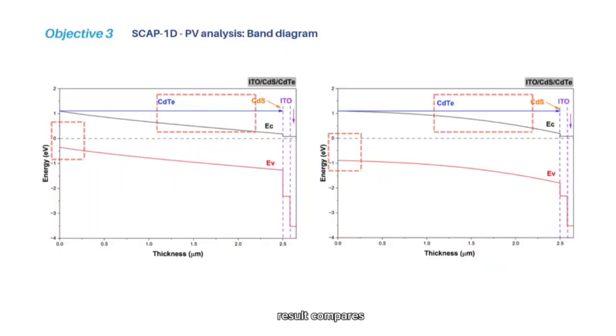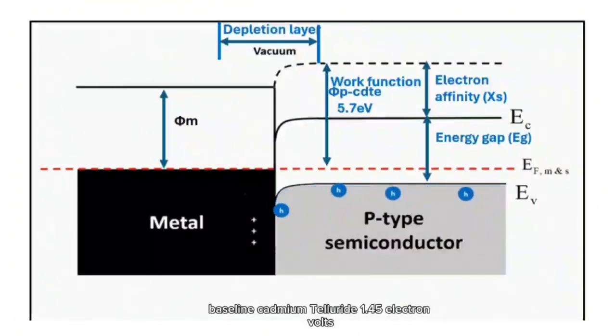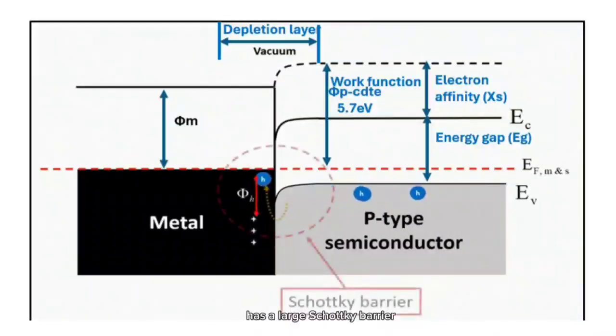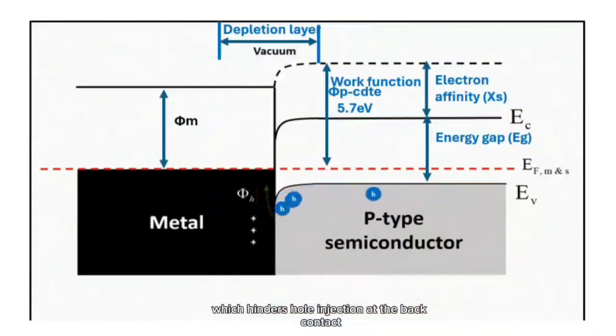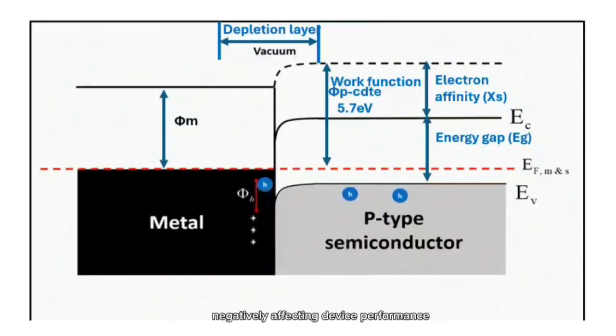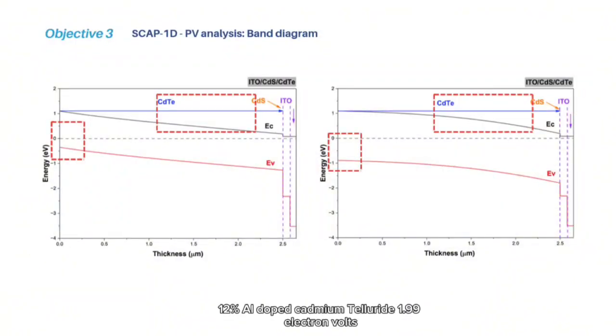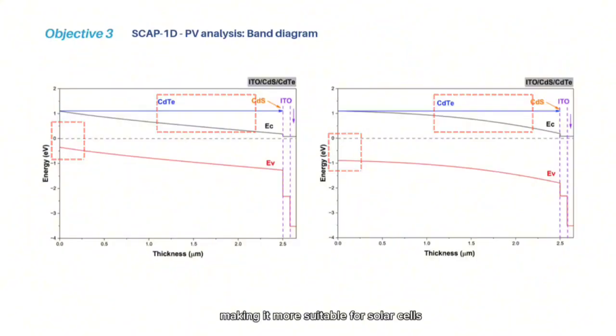This result compares baseline cadmium telluride and 12% Al-doped cadmium telluride, showing the impact of Al doping on the band diagram. Baseline cadmium telluride, 1.45 electron volts, has a large Schottky barrier, which hinders hole injection at the back contact, negatively affecting device performance. 12% Al-doped cadmium telluride, 1.99 electron volts, reduces the Schottky barrier, improving hole collection and electron conductivity, making it more suitable for solar cells.